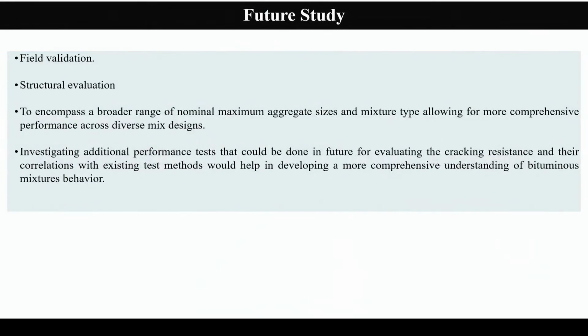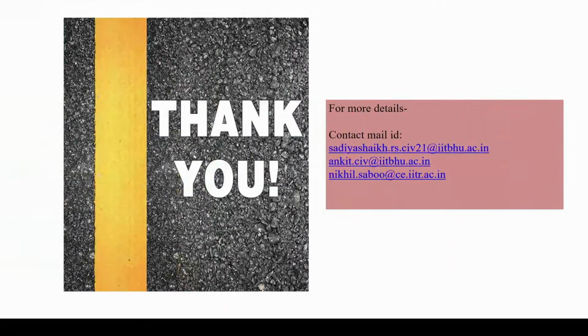And the one suggestion is that, as we have the moisture test, the TSR of 0.8, or you can say 80%, two more tests can be added, like the permanent strain values, the minimum value and the maximum value, and for the CT index, the minimum value could be added in the code after the field validation part. Some studies are still going on, and we will come up with modified thresholds, and with a better threshold, it will lead to the most cost efficient, durable, and long lasting pavement. Thank you. That's all.